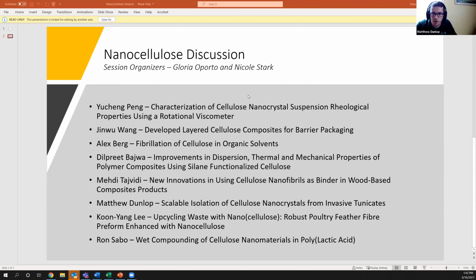And actually working with Dr. Sabo at the Forest Product Laboratory, we used polylactic acid as another matrix to try and see if we could do extrusion melt mixing processes with these CNCs and preserve this hybrid reinforcement. So using PLA, we prepared cast films and extruded films by solution mixing and melt mixing techniques.